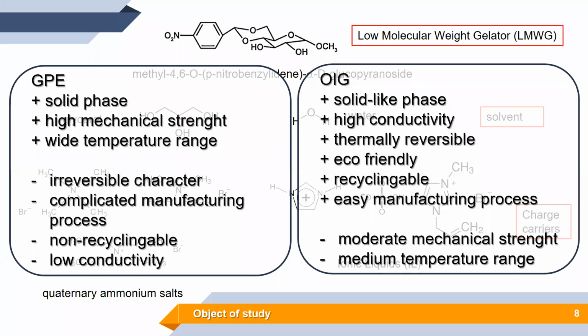The drawbacks or the weak side of the system is that because of the physical nature of the forces that create the gel phase, the mechanical strength of such a system is rather moderate, and the temperature range in which the gel phase exists is also medium. However, recent research in developing new low molecular weight gelators has already given examples where the temperature range is over 120 degrees, which is already good for applications.